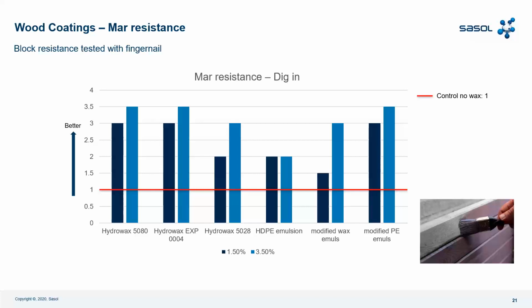Then we have the best results with respect to all Sasol wax emulsions from Hydrowax 5080 and Hydrovax experimental 004. And if we increase to 3.5%, we can see that the mar resistance dig-in performance increases. Again, we have Hydrowax 5080 and Hydrovax experimental 004 outperforming, followed by Hydrovax 5028. At 3.5%, we have a similar performance to the modified PE emulsion.